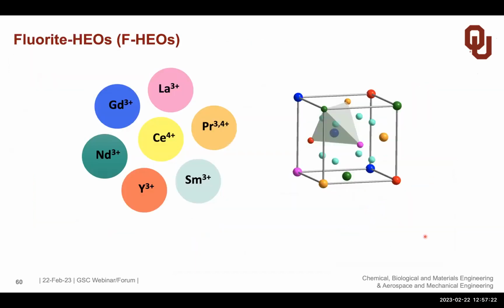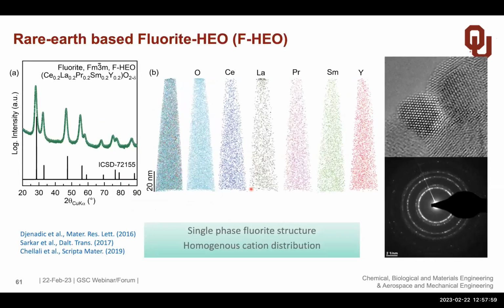I showed you that other materials can also be prepared. And here is an example of the fluorite structure, which is shown over here, rare earth type of systems. They're interesting not only because they address different properties, in particular optical properties and band gap, but they also have a rich variety of different valencies the ions can have. But it also shows in this case that the 4+ ion cerium is very important to stabilize the structure.